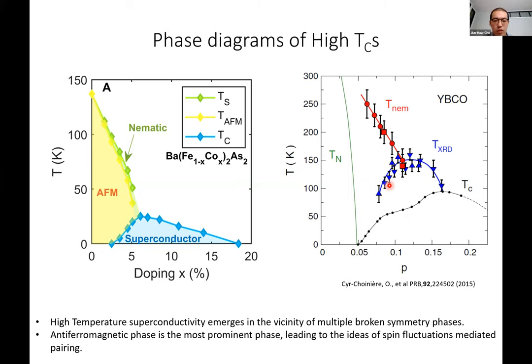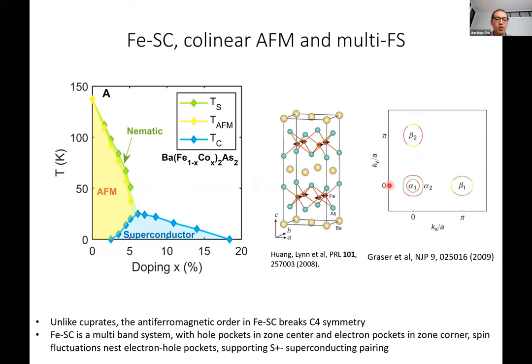But if you take a further look, then you can start to see the difference. For example, in the iron-based superconductor, the antiferromagnetic phase actually forms a collinear antiferromagnetic magnetic order that breaks the crystal C4 symmetry. The iron spins are aligned ferromagnetically along one direction and then aligned antiferromagnetically along the other direction. And this ordering wave vector has a special implication when you're considering the Fermi surface of these materials.